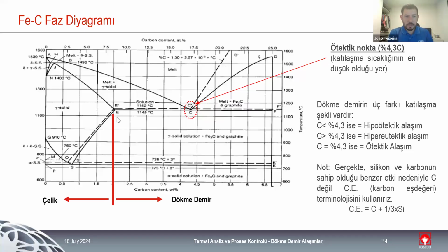We can distinguish the solidification type based on the amount of carbon that we have. If we have 4.3%, we have the eutectic point. We call it a point, but in reality, it's more of a smaller area. It's not considered a point, but for easier explanation, we call that a point, around 4.3%. It's a eutectic solidification. It's the eutectic point of cast iron.